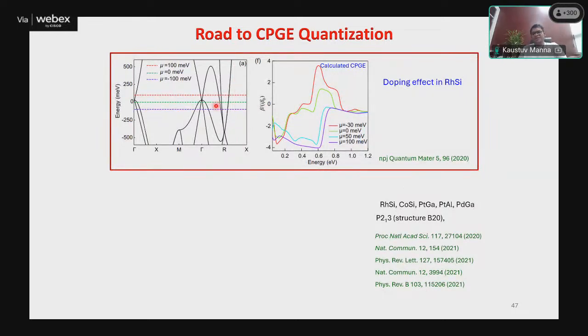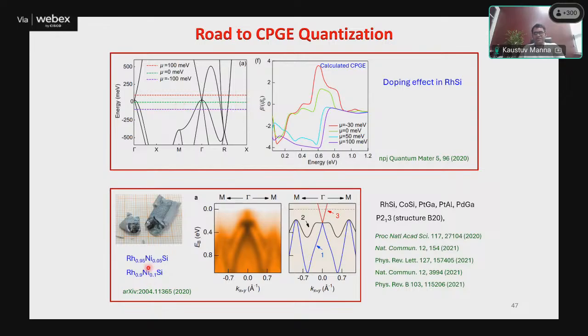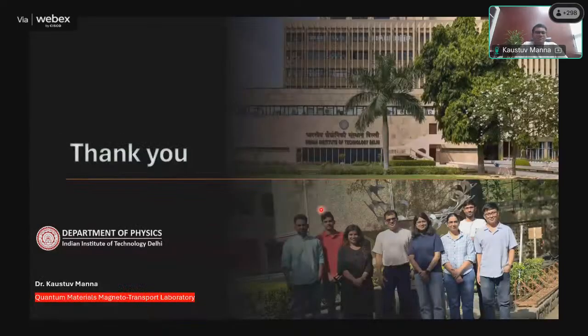There are many theoretical calculations showing that the Fermi energy can be tuned. How can it be tuned? We can dope rhodium silicide with nickel, and we can shift the Fermi energy. In fact, in my nickel-doped sample also, we have shifted the Fermi energy from this point to above. So like that. Oh, it's already over.